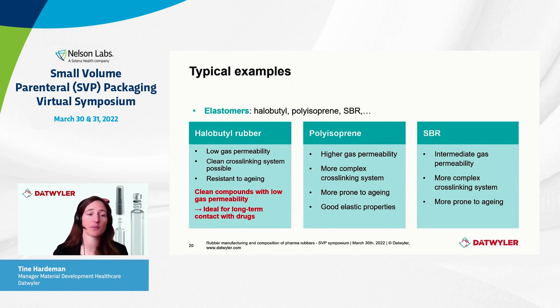But within the pharma segment, halobutyl rubber is the first component of choice, and this actually has a number of good reasons. So there are three important advantages that this halobutyl rubber has that makes it so popular. First of all, there's a very low gas permeability, which means that oxygen cannot come into the system, and also water vapor cannot go out. Second, it's also possible to cure halobutyl rubber with a clean cross-linking system. So you don't need to add too much harsh or dirty chemicals, in fact, to make the vulcanization reaction happen, which is a great advantage if you want to have a clean rubber. And also it's quite resistant to aging in itself, which means that you don't need to add too much antioxidant to have a good rubber with a long shelf life.